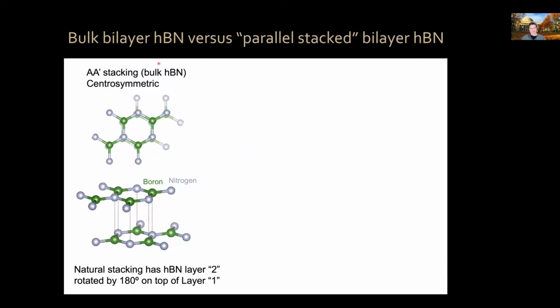So the example that I want to think about is bulk bilayer hexagonal boron nitride, and compare it with parallel stack bilayer boron nitride. Bulk boron nitride is a material which has a stacking which is known as AA' stacking. It is centrosymmetric. You alternate the boron and nitrogen atoms in the crystal structure. It's similar to graphene, but now with boron and nitrogen atoms in the A and B sublattices, and they alternate in the vertical direction. So natural stacking has hexagonal boron nitride layer number 2 rotated by 180 degrees on top of layer number 1.